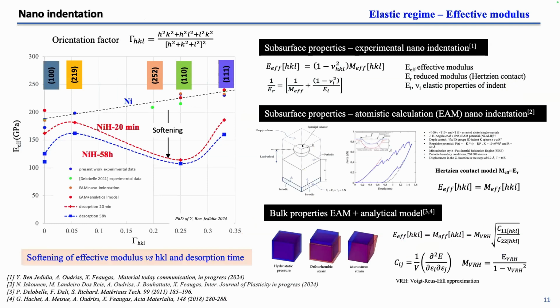Okay, the result of effective modulus as a function of orientation factor, like that. HKL is the orientation of the plane. And we compare here the effect of the orientation without hydrogen, and here is the result with hydrogen. The main effect is softening, and it depends on the orientation. To discuss that, we use diffusivity, and we also use modularized atomistic calculation. Two kinds of approach, we do not describe that.